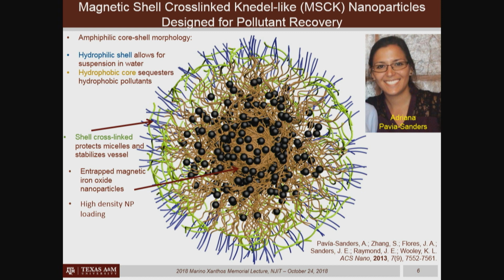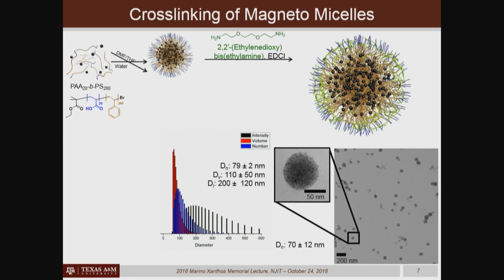Now, Adriana Pavia-Sanders was a young PhD student in my group when the Deepwater Horizon oil spill occurred, and she got excited about trying to build these nanostructures to address, again, that challenge. And so, they were designed in such a way as to have inorganic magnetic nanoparticles trapped within a polymer framework, where that polymer framework would have hydrophobic polymer chains within a core domain surrounded by hydrophilic polymer chains that are then cross-linked together to stabilize the entire entity as essentially a nanoscopic single molecule containing these inorganic particles.